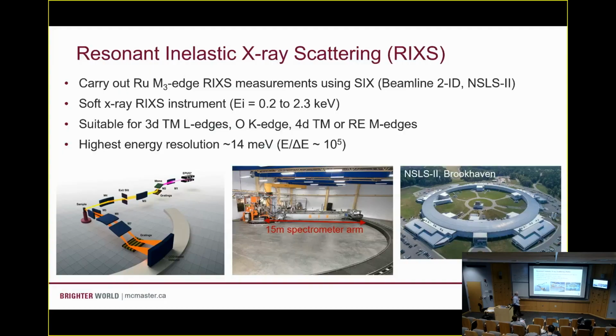Okay? The energy resolution for RIXS is typically on the order of tens of milli-electron volts, okay? Which does not sound that impressive until you realize that the incident energies are about 10 to the 5 times higher than that. So as a relative energy resolution, these instruments are really amazing. And SIX in particular, to get this high energy resolution, 1 part in 10 to the 5, has a 15-meter moving spectrometer arm, which has to be controlled with incredible sub-millimeter precision. So it's a very neat instrument, and so big that it requires its own addition to the ring here.